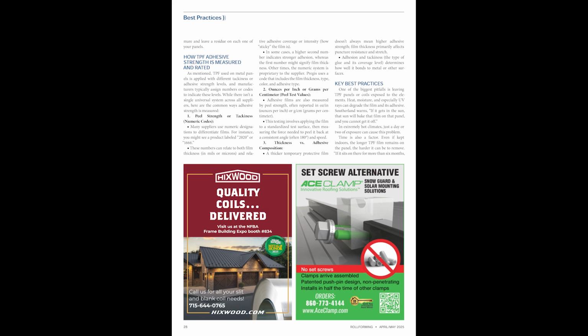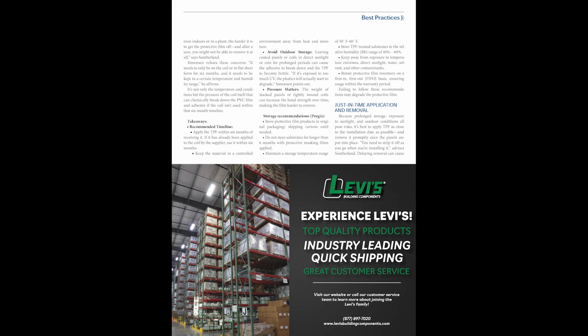"If it sits on there for more than 6 months, even indoors or in a plant, the harder it is to get the protective film off, and after a year, you might not be able to remove it at all," says Sutherland. Simonson echoes these concerns. "It needs to only be on the coil or in flat sheet form for 6 months, and it needs to be kept in a certain temperature and humidity range," he affirms. "It's not only the temperature and conditions, but the pressure of the coil itself that can chemically break down the PVC film and adhesive if the coil isn't used within that 6-month timeline."